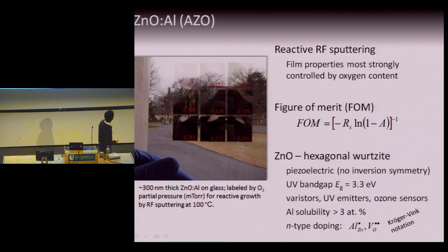In the lab, I grow aluminum-doped zinc oxide by reactive RF sputtering. That's a physical vapor deposition technique. The film properties are most strongly controlled by varying the oxygen content. This is just a gratuitous picture I took outside of our building, showing what happens when you go from low oxygen content to high oxygen content. This film you can't see through very well, but it conducts electricity very well. This is closer to just a messy metal. This material up here you can see through, but it doesn't conduct electricity at all. In between is an optimal material for technological applications.